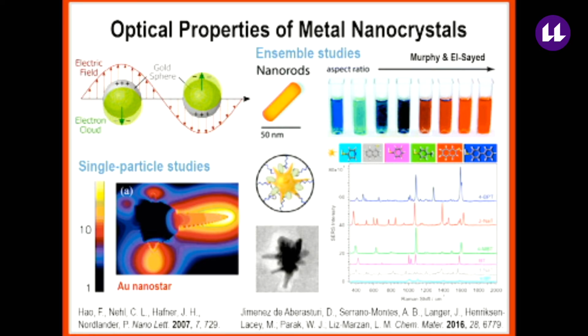And part of the reason why we were so interested in these nanocrystals is because of their optical properties, how gold nanocrystals have a strong localized surface plasmon resonance, or collective oscillation of our conduction electrons in response to the change in electric field. And we just saw earlier today and at the beginning of the week all the interest in gold nanostars. And gold nanostars are tremendous nanocrystals where, because of the sharp tips with a small radius of curvature, you have that large electric field enhancement that can bring about large enhancements in surface-enhanced Raman spectroscopy, just as we heard this morning.